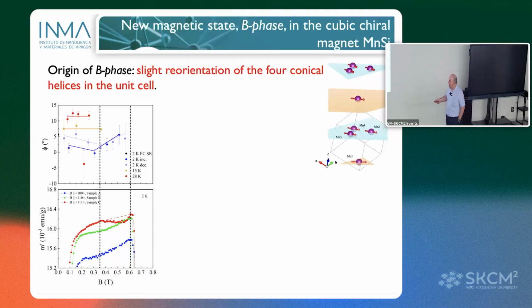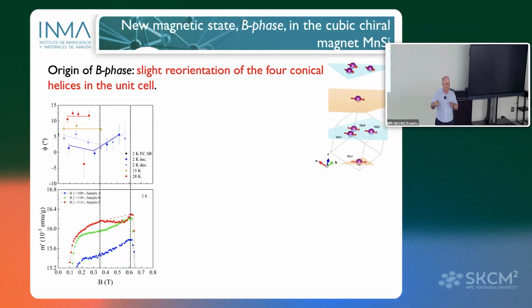And this cannot be described by the model that I told you at the beginning, because in the theoretical model the modulus of the magnetic moment was fixed to 1. And here, the fact that you are moving the angle between the helices produces a change in the modulus of the average of the four spirals. And this is described by the theoretical model. Then it's not surprising.